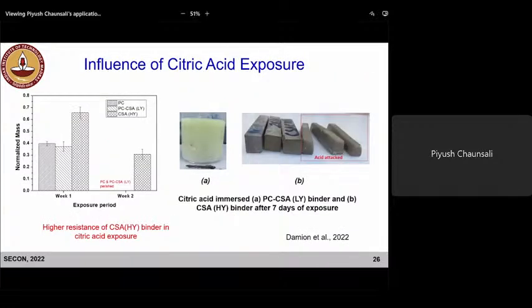Okay, so this is some of the recent work from our lab here at IIT Madras. We are looking at also the durability. Because of the high alumina content of CSAB cement, they are a potential candidate for applications such as sewage pipes, right, where the concrete is exposed to acidic environment. So we are looking at acid resistance of CSAB cement concrete, with citric acid being the most deteriorating acid. We looked at that, and you can see.